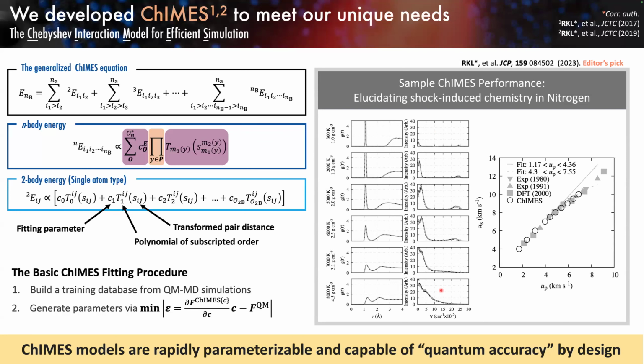We can also compare these things to experimental data. So here we use this model to predict the shock Hugoniot for nitrogen. And so now if you look at the up and down triangles that start about here and end about here, these are experimental measurements. And then these open circles are what ChIMES predicts. And so we can validate against experiment. And then we can take this a step further and say, well, why don't I dig into my simulation and provide information on the time-resolved structural evolution or the time-resolved chemistry that takes place during this shock compression, for example. So just to kind of give you a sense of things.